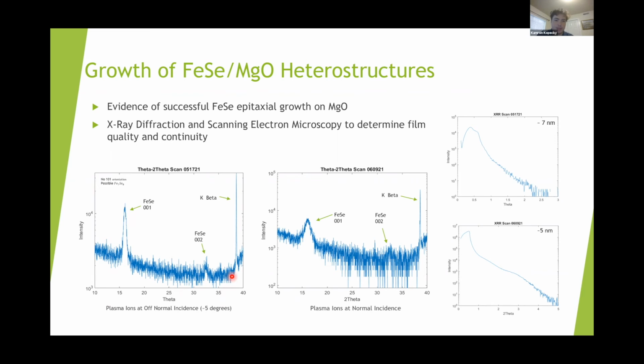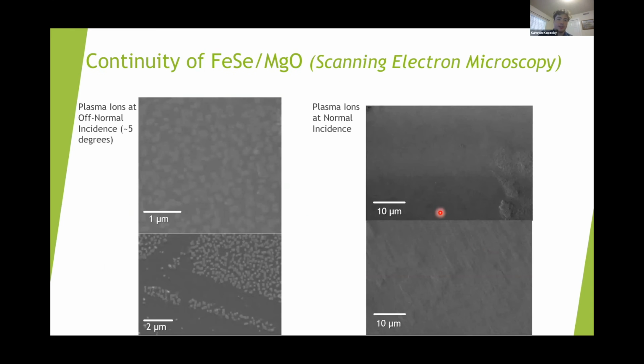normal incidence of the plasma plume, and where the plasma ions were at normal incidence, in which the iron selenide layer on the magnesium oxide is C-axis oriented and epitaxial in both cases. And there are minor differences in the thickness of these layers through X-ray reflectivity. We can find the thickness from fitting these curves. But the major difference between the off incidence and the normal incidence is the continuity of the film.